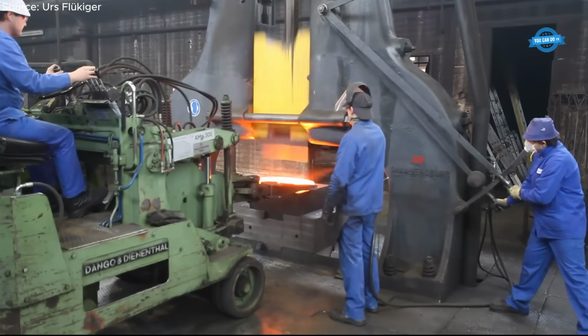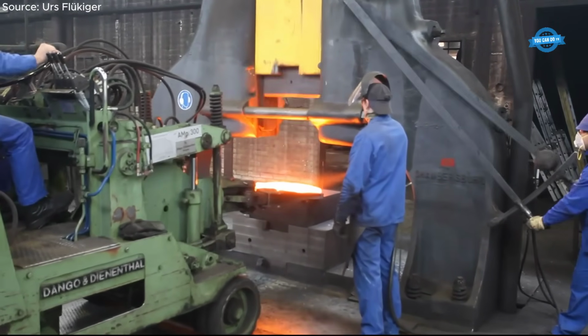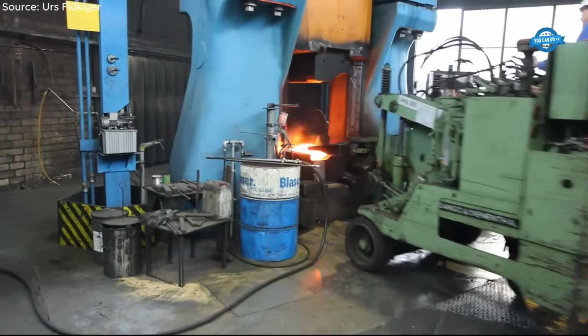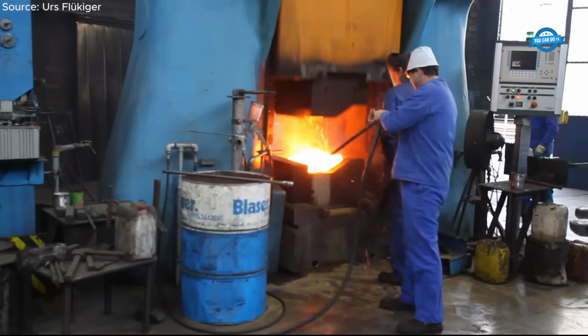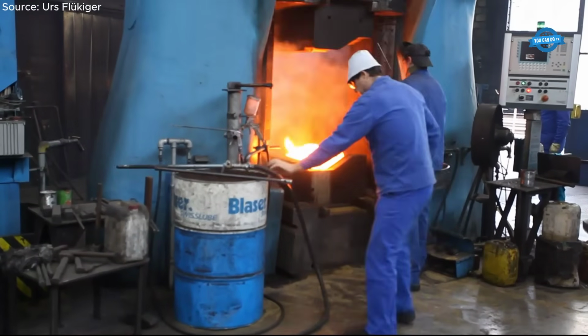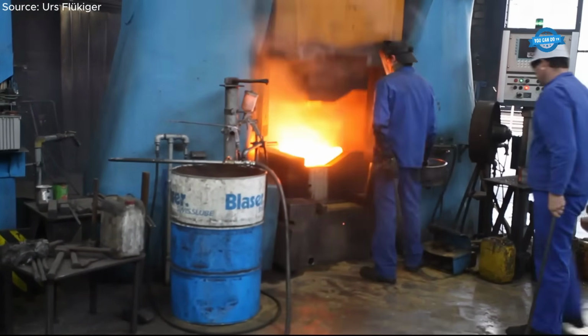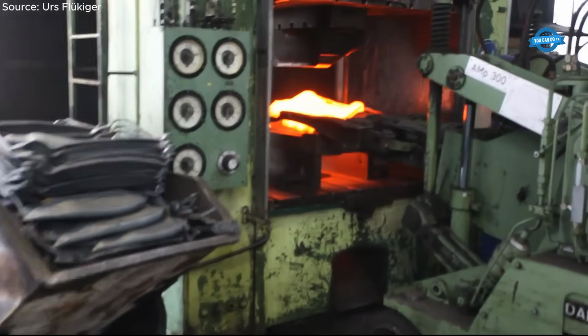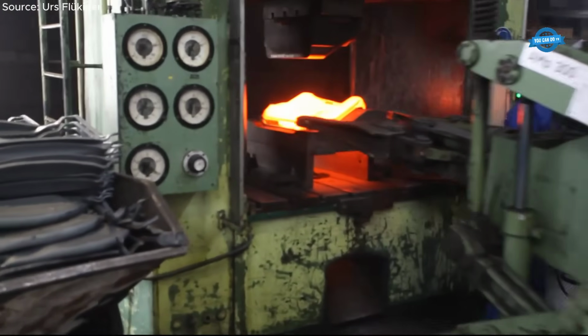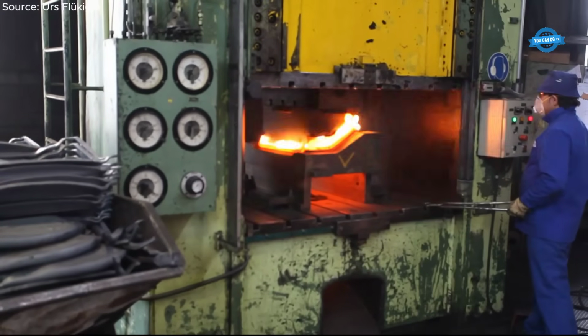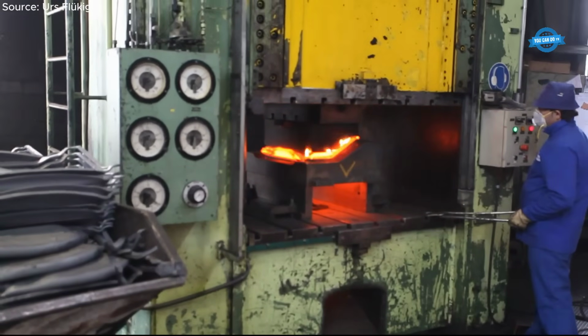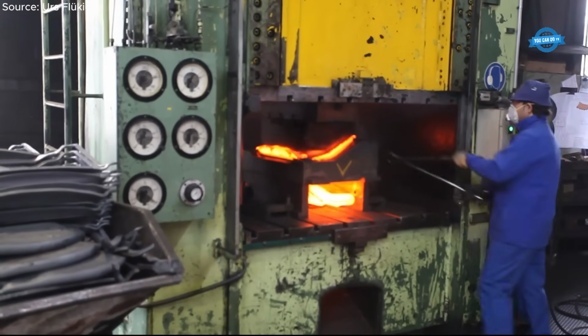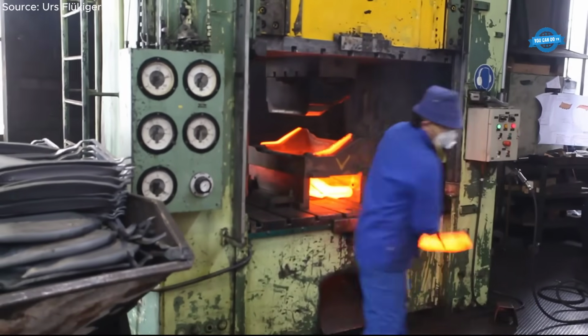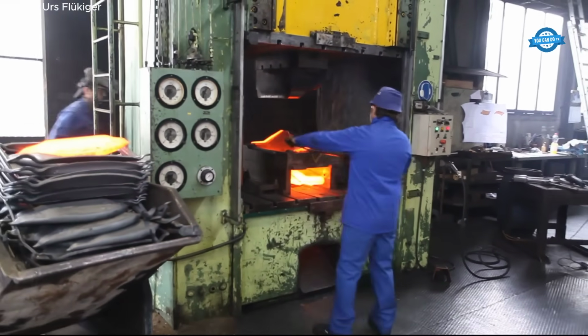The forging process of a locomotive chassis part, approximately 100 kilograms of steel, involves rough shaping with a pneumatic hammer, 900 kilojoules, 1959, and further forming with an electro-hydraulic die hammer, 1,250 kilojoules, 2003. The work requires 3 heating cycles, 1,200 degrees Celsius, and over 100 blows, completed with trimming presses.